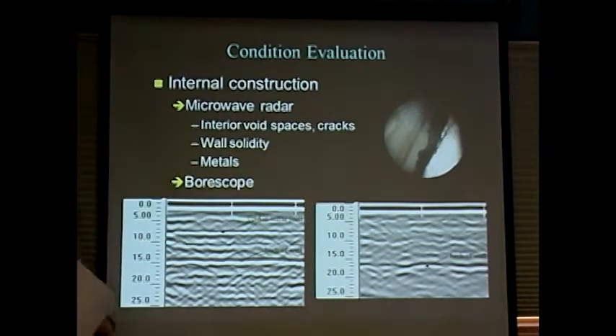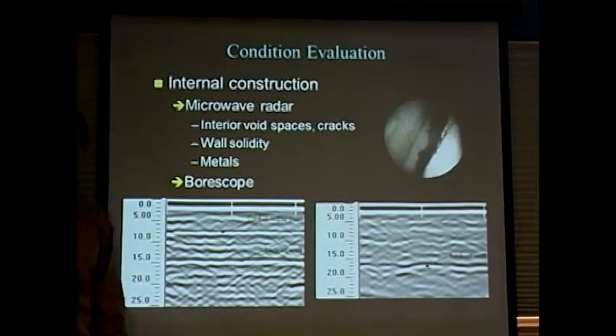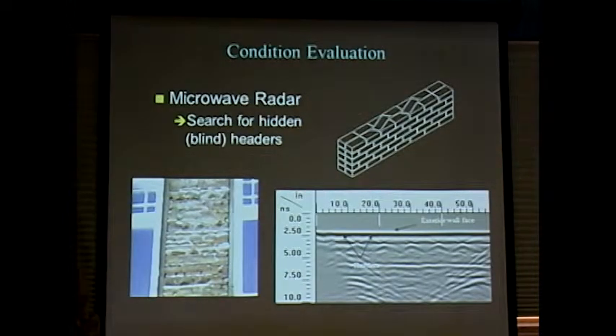Borescope, there's a borescope image, and looking down inside the wall, you see brick and mortar and a void space, and that's pretty typical. Whenever we think there's voids inside walls, we like to open things up and look at it with a borescope, and that's just inserted through a little 1/2-inch diameter hole drilled into mortar joints.